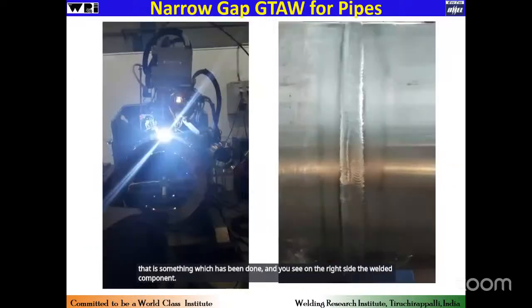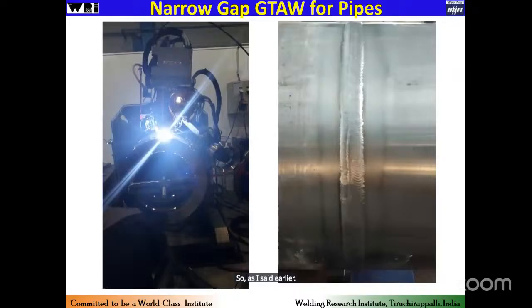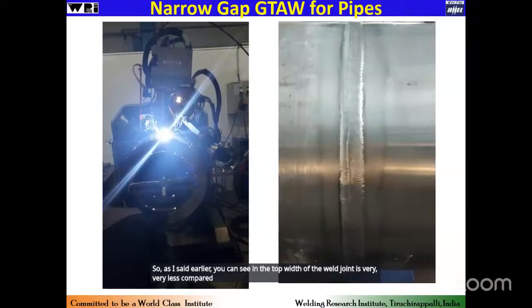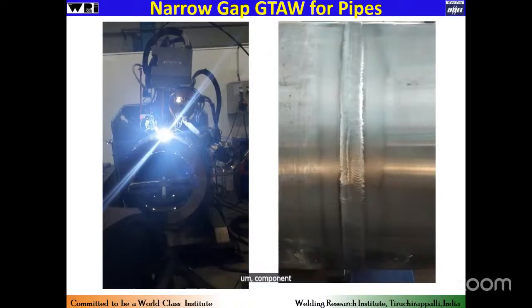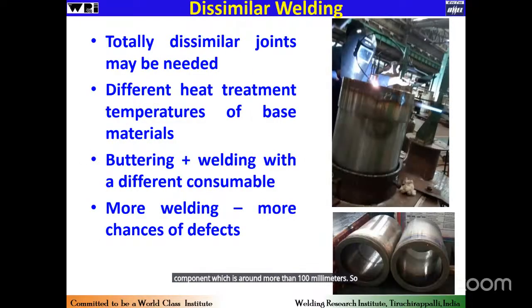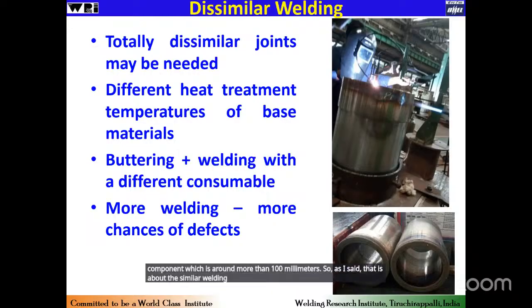So as I said earlier, you can see the top width of the weld joint is very, very less compared to the thickness. So top width will be only 10 to 15 millimeters for a total thickness of component, which is around more than 100 millimeters. So, as I said, that is about the similar welding, but it will also need dissimilar welding combinations as well.